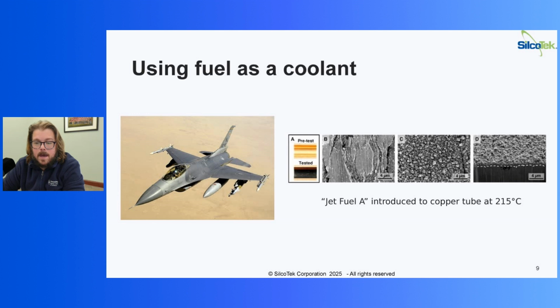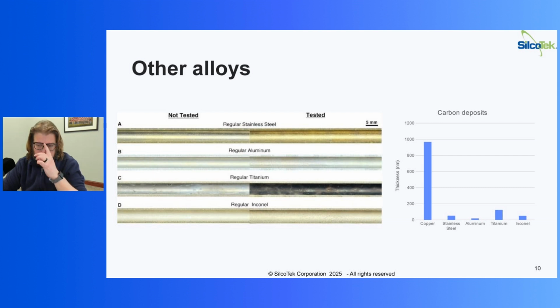And under SEM and using FIB cuts, they were able to take a look at the thickness of that carbonaceous material that gets deposited onto the surface of the copper tube. So copper's not great as far as carbon deposits are concerned. It will deposit a lot of carbon relatively quickly. You can see on the right-hand side here is basically the chart showing copper really off the charts compared to some of the other alloys that they tested.